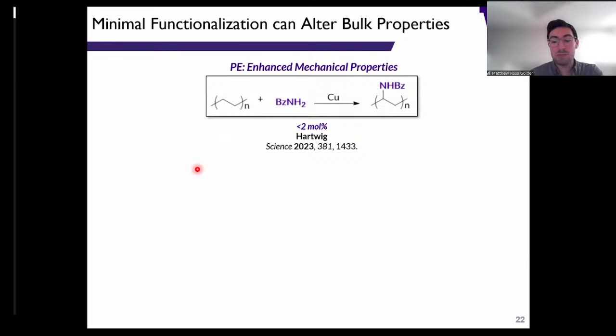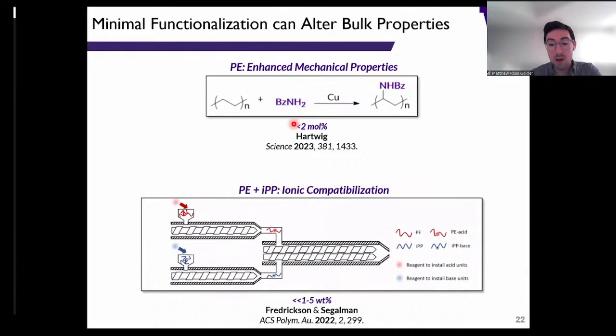What I want to emphasize is that you don't have to do a lot to the backbone of a polymer to really change its function. You can get minimal functionalization that can alter bulk properties. So in this case, we have polyethylene. This is an example from John Hartwig's group. The copper catalyzed amination of the polyethylene backbone. And even at less than 2 mol% tagging, you can get drastic enhancement in downstream mechanical properties. This is work from Fredrickson and Segalman that shows that you can actually tag two traditionally immiscible polymers.